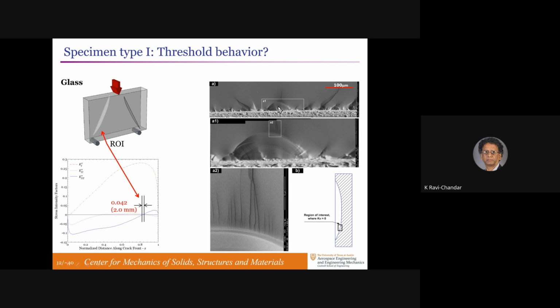What this implies is that there's no threshold. The instant you apply a mode 3 of non-zero value, the crack wants to find the space in which it tilts and creates a mode 1 crack, and not a flat crack with mode 1 and mode 3 acting simultaneously. This is a glass.